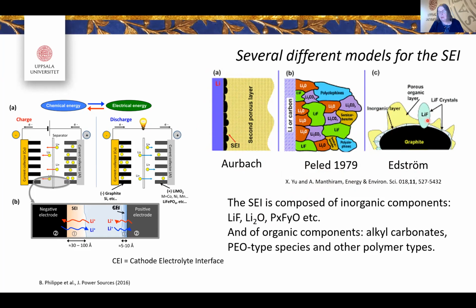But depending on how you treat your electrode, you get crystals of lithium fluoride, and these crystals can be of very varying size, dependent on how you have treated your electrode, what anion you have in your lithium salt, etc. So, over-exaggerating also the heterogeneous type of layer you have on the surface. It's actually here in this model as well that it's heterogeneous.